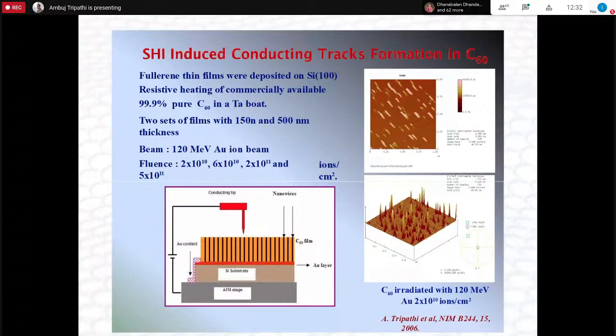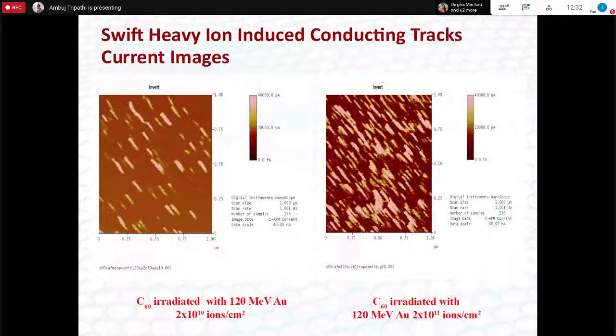A very simple way of doing it is to correlate it with the number of impacts. If you increase the fluence 10 times, you should expect the number of tracks to increase with the increase in fluence. As you can see in the two images, this one is done at 2 into 10 to the power 10 ions per centimeter square. The right side image is done at 2 into 10 to the power 11. So you go 10 times higher, and then you expect the number of impacts, these bright spots you are seeing, to be 10 times higher. And then you can do characterization on that.